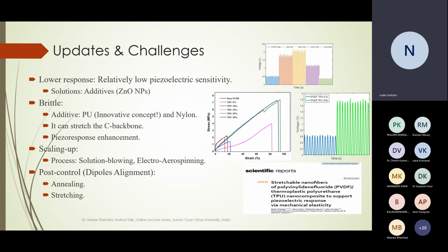Also, one very famous challenge for the PVDF nanofibers is that they're brittle. They cannot withstand different mechanical excitations, especially stretching. Most likely the elastic strain level or even the breaking strain level could not, in most cases, exceed 5 or 6%. So this is a very tough range for different industrial applications.